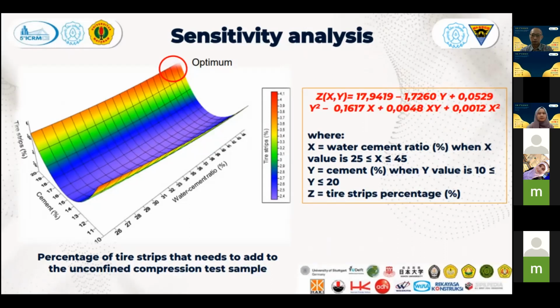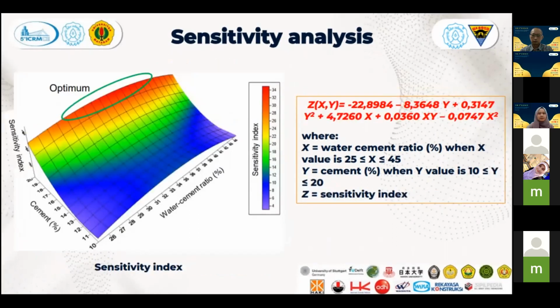Based on the 3D statistical model, we can get the percentage of tire waste that needs to be added to the unconfined compression test sample. Based on this analysis, the percentage of tire waste can be found with this equation, and the maximum percentage of tire waste addition is 4.05%. And the second step of sensitivity analysis is determining the sensitivity index for the addition of 3% tire waste for a water cement ratio of 45% and 20% of cement using 3D statistical models.